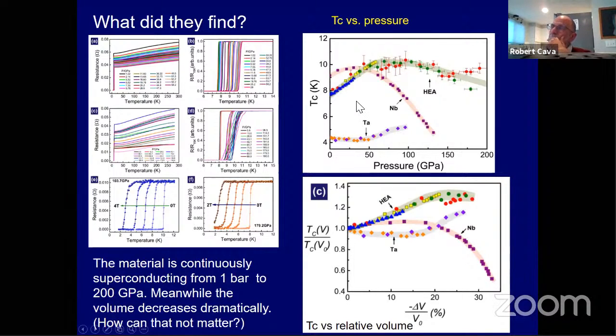So what happened is, when Jing and Li Ling put this high entropy alloy under pressure, they found that the TC went up dramatically first, and then it stayed superconducting up to 200 GPa, which is a ridiculous high. That's 2 megabars of pressure. And I eventually got them to measure pure niobium and pure tantalum, which do something different. So the high entropy alloy, even though you might say, well, it has tantalum or niobium in it, and so it must be the same as them, it's not the same as them. It's something different. So its TC continues to go up, and it's still there at 200 GPa.